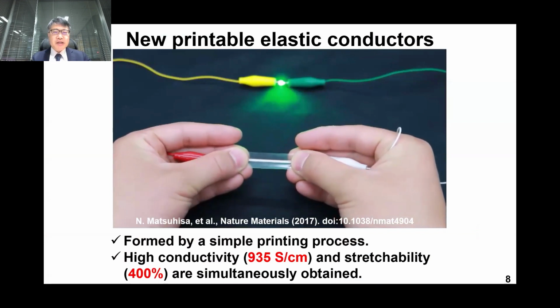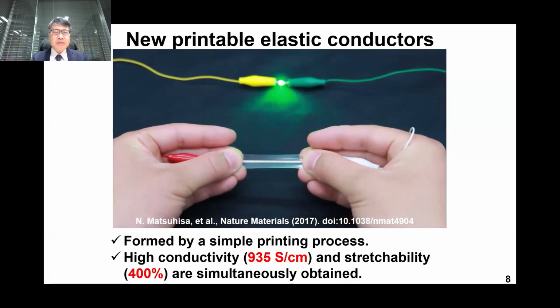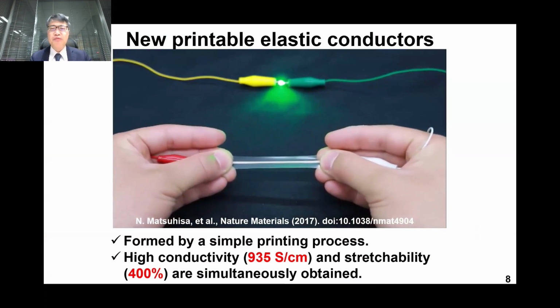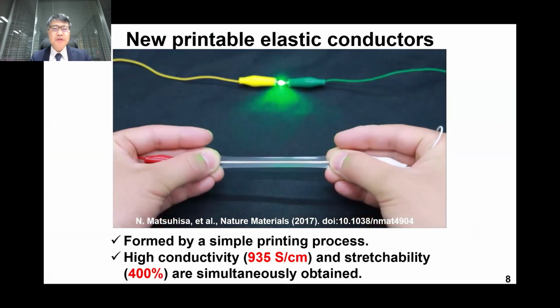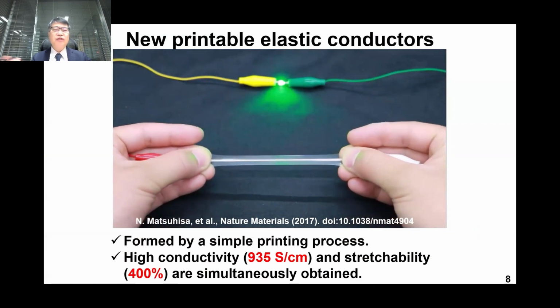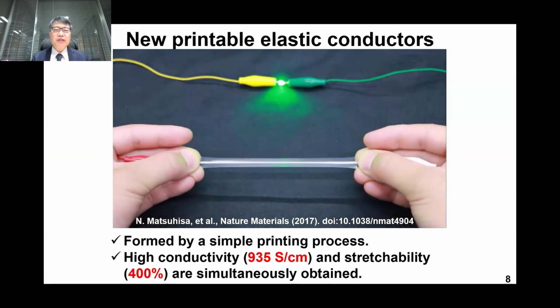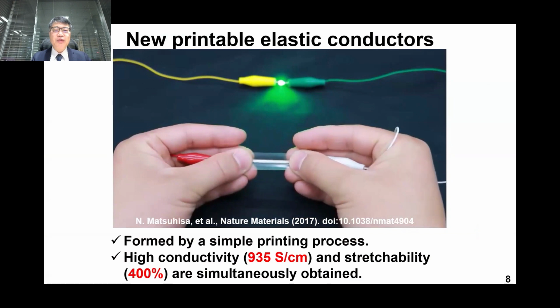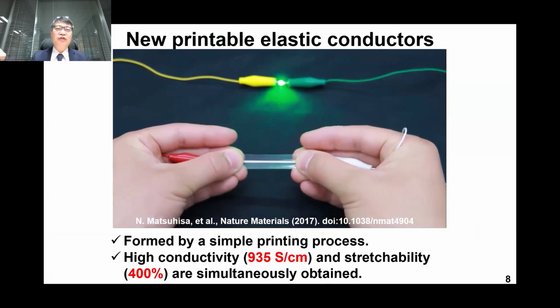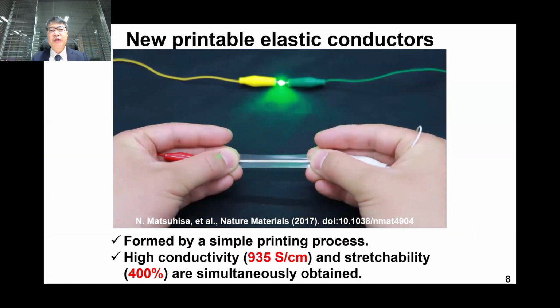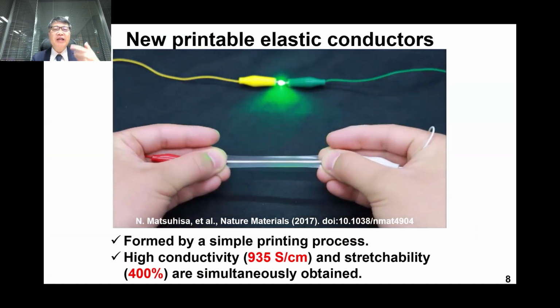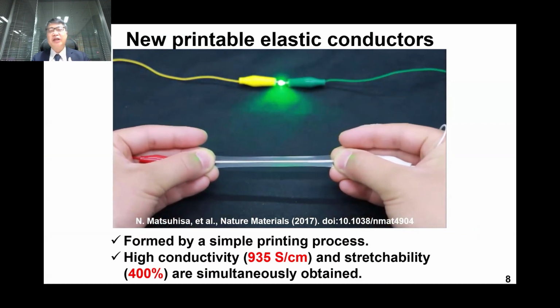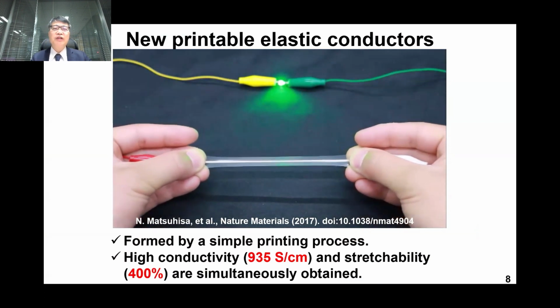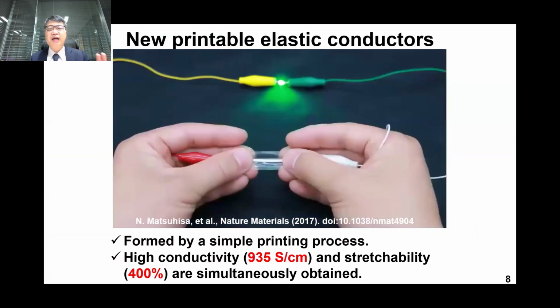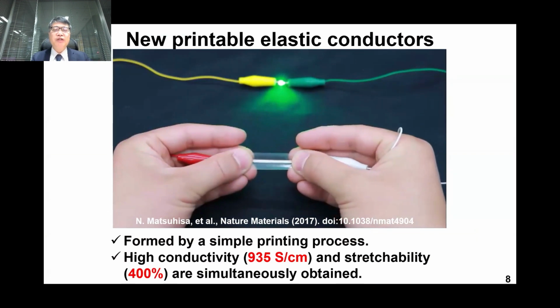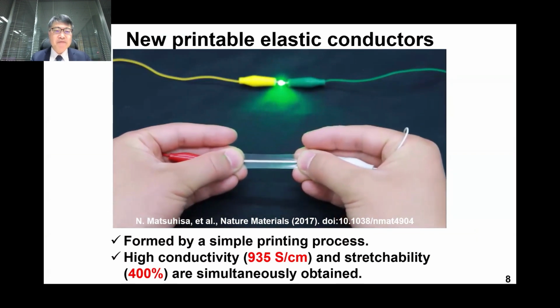So here, the newly developed printable elastic conductors play a very important role. You may see how the new material works. We stretch our material printed on an elastic substrate and connected to a light-emitting diode and battery. You didn't see any change of light intensity from the LED. That means the change of resistivity could be suppressed sufficiently low.